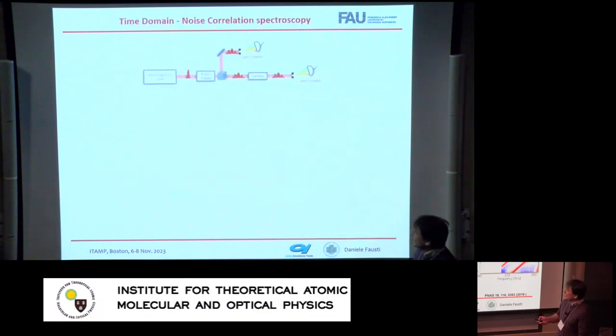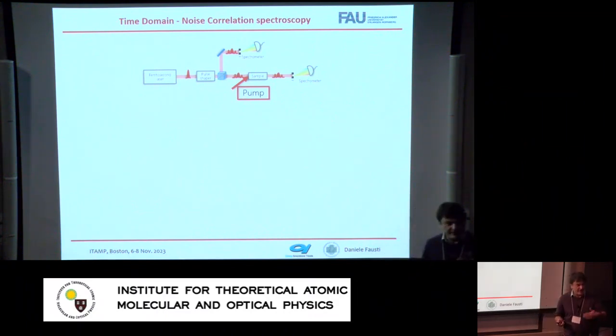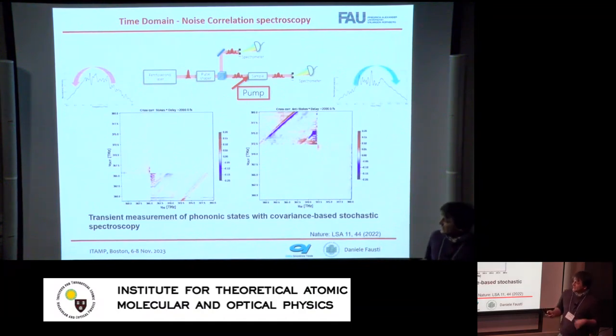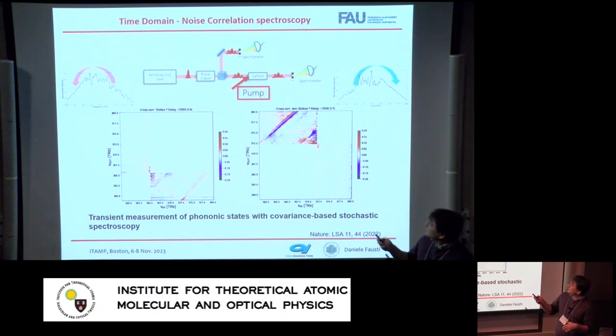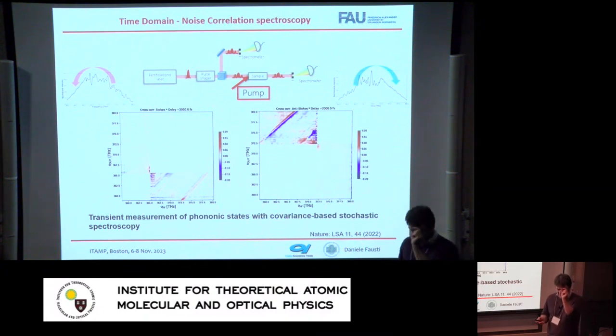As I said, the good thing of this setting is that now I can go to a pump and probe setting, so I can perturb my sample, so prepare an excitation in the sample, and I can look at the time evolution. So I will measure the time response of the sample, which has a very high frequency resolution, because the resolution in frequency is given by the width of the noise, while on average a very high resolution in